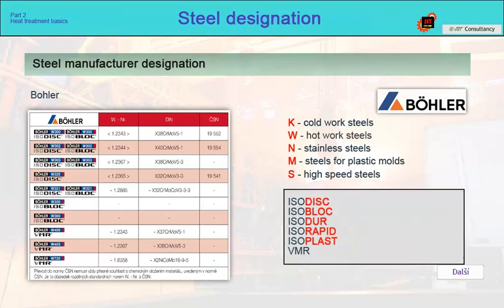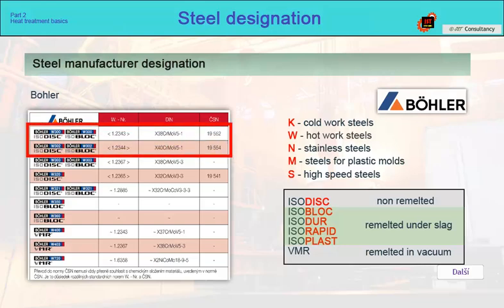Another distinction between steels is in the remelting process. Isodisc steels are non-remelted. Isoblock, Isodur, Isorapid, and Isoplast steels are remelted under slag, and VMR steels are remelted in vacuum. However, for the heat treater, if the manufacturer's steel grade name is stated in the drawing, it must be followed by the Böhler regulation for this material, although in some cases there is an equivalent according to EN.